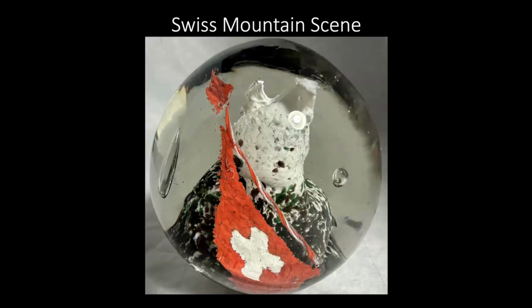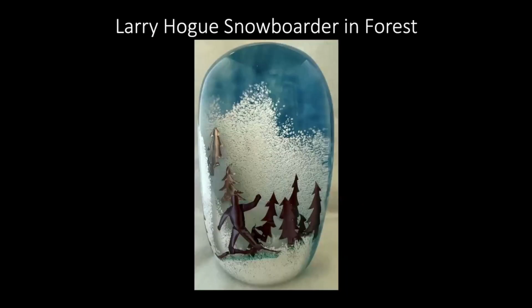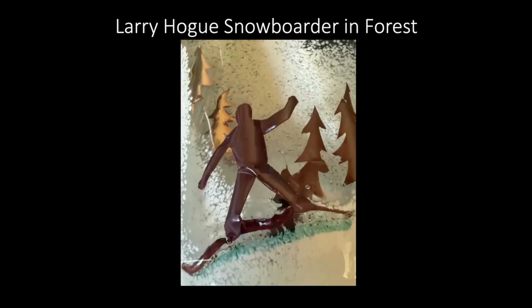This was another antique store find, unsigned, snowy mountain with a Swiss flag. This was a recent acquisition. Got it last year from Larry Hogue, who's up in Seattle, Washington. It's a winter scene, a snowboarder in trees. These are copper inclusions. You can see the copper color in the trees in the back. The front trees and the snowboarder turned red from the heat of the encasement process.